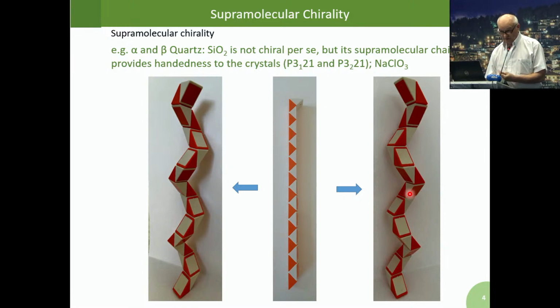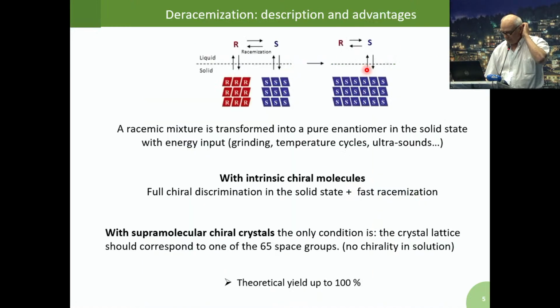Example of that is quartz, alpha quartz, beta quartz. SiO2 is not chiral in itself, so when you have a liquid, you don't have any chirality. But if you crystallize them, and then you obtain for the alpha quartz, P3 1-to-1 or P3 2-to-1 for the other enantiomer, which means that you have built supramolecular assembly, which are themselves chiral. So now we can use that to obtain homochiral crystals.